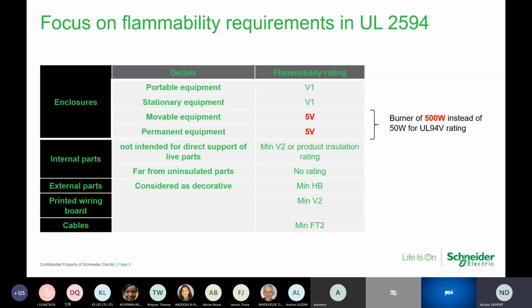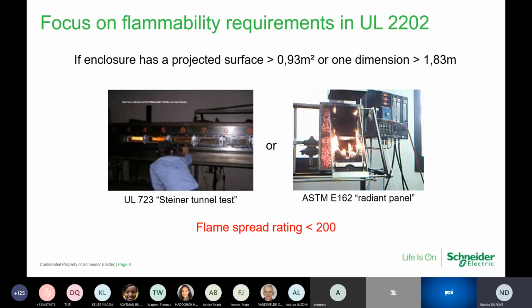In the UL 2202, it's even worse because there is an additional test which is required if the enclosure has at least one dimension which is exceeding 1.83 meters or a projected surface larger than 0.93 square meter. This test can be either the Steiner tunnel test or the radiant panel, but in both cases, the flame spread rating should remain lower than 200.